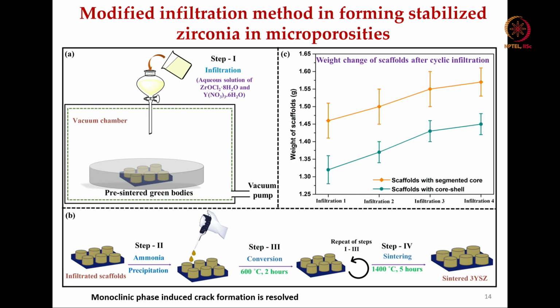So, what we have used is the modified infiltration method. In the modified infiltration method, we use zirconium oxychloride 8H2O together with yttrium nitrate 6H2O. So, this is the precursor solution. In a vacuum, we infiltrate drop by drop into the pre-sintered green bodies. Pre-sintered green bodies can also mean 3D binder jet printed materials, right.